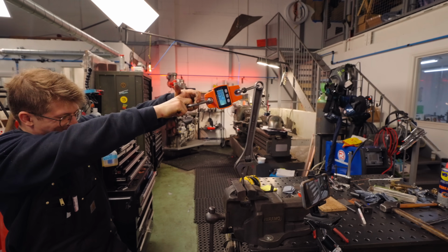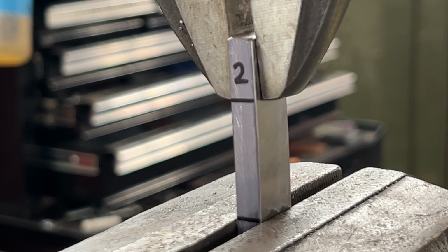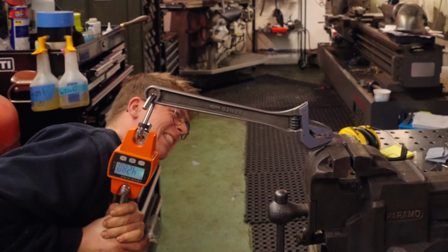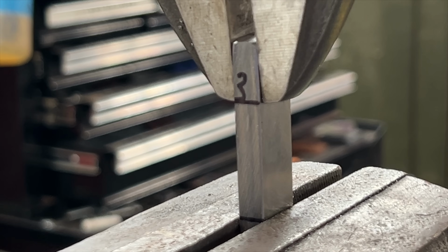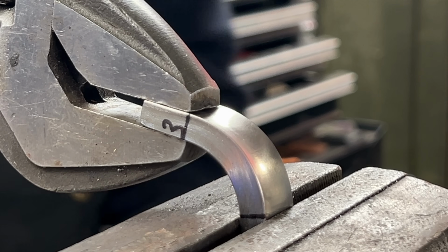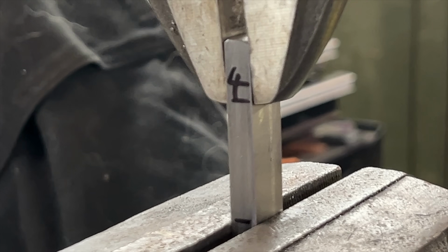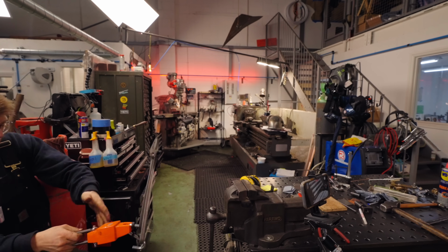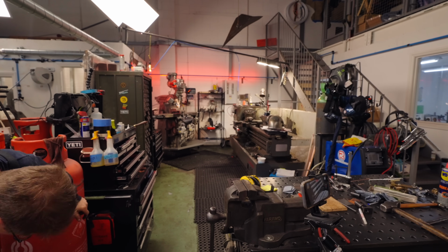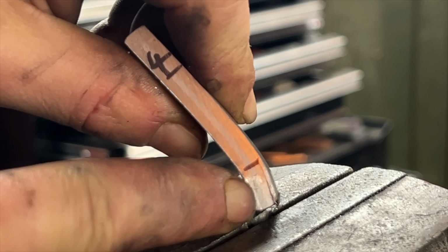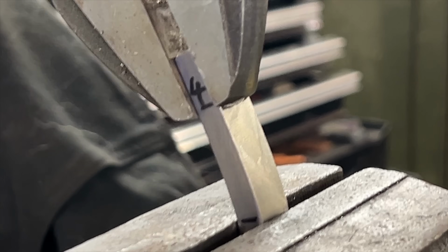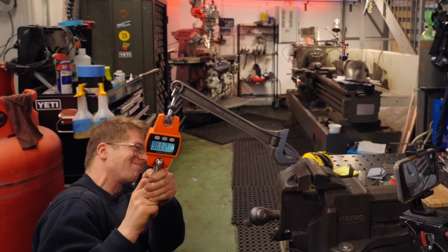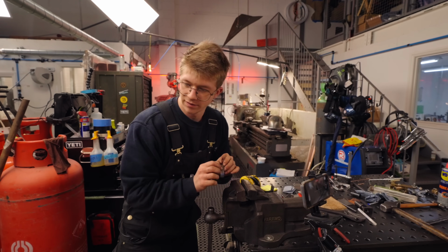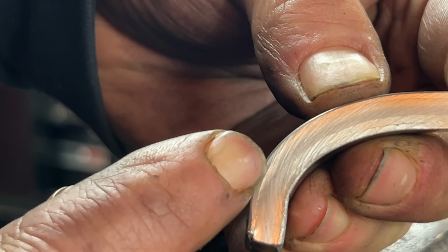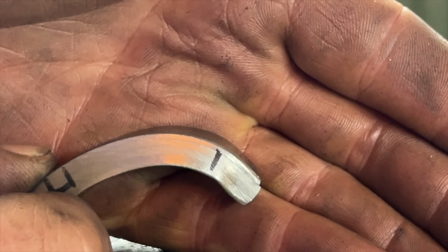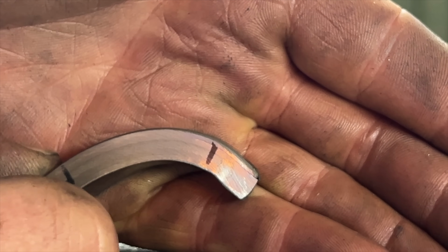2. Oh my gosh, that's hard. 3. This is great. 4. Oh! It delaminated a little bit and then just popped out. 4, take 2. Oh, it's cracking. Impressive. It has a little bit of delamination propagating up on the bend. It's on the outer edge. That's between the grade 5 and the grade 2 titanium.